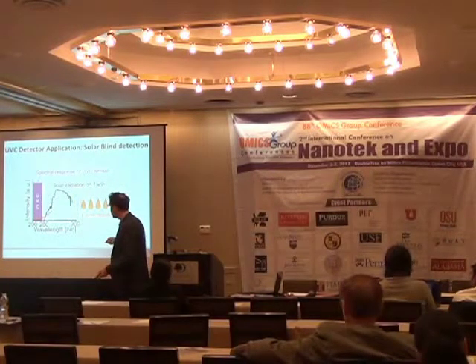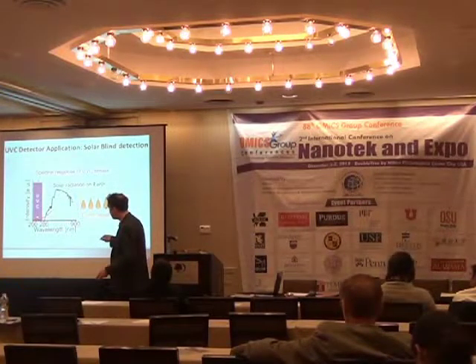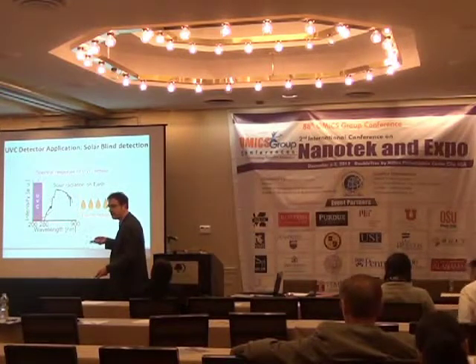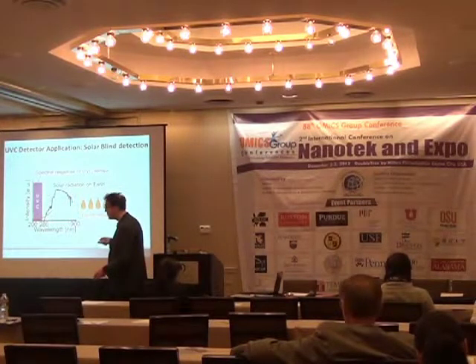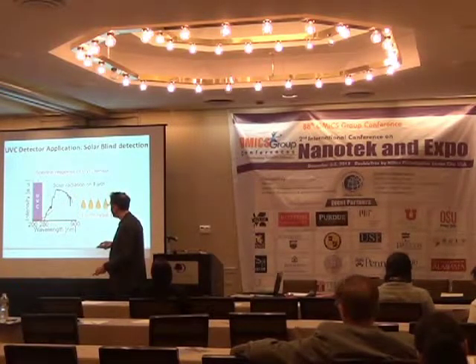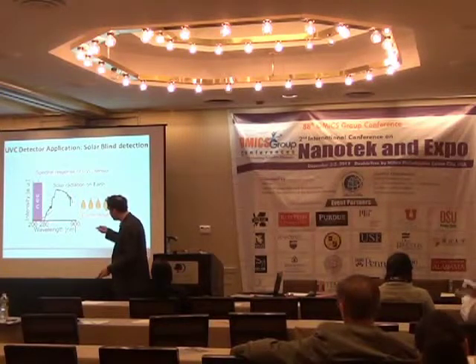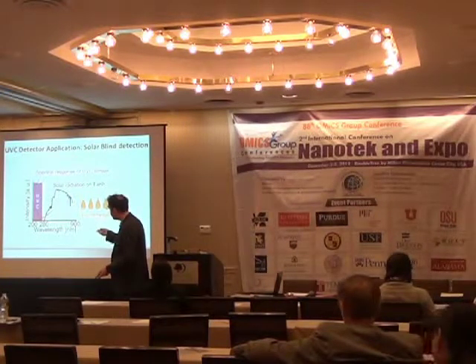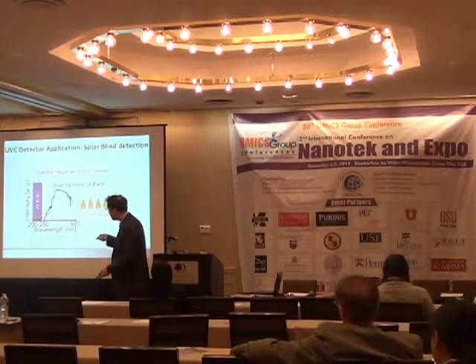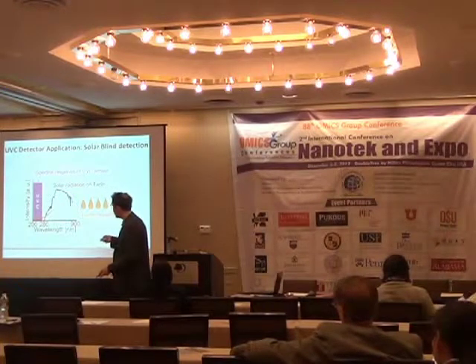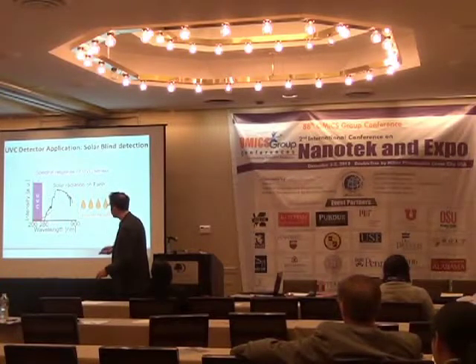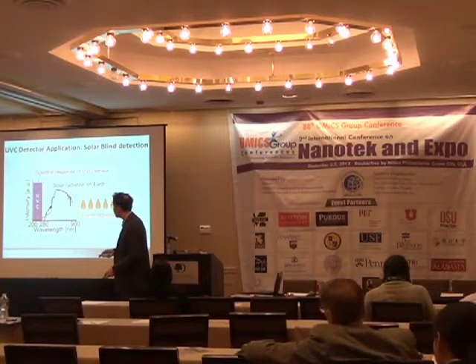Good. So why is this interesting? Because you have a high signal-to-noise ratio, the noise being the background, which is very low, so the signal ratio is very high, and therefore this technique is quite sensitive. Okay. And for that technique to work, you need this type of spectral response where you are sensitive to UVC radiation only, below 280 nanometers. So you need to be solar blind. You need to be not sensitive to solar radiation. That's the point of this solar-blind detector.